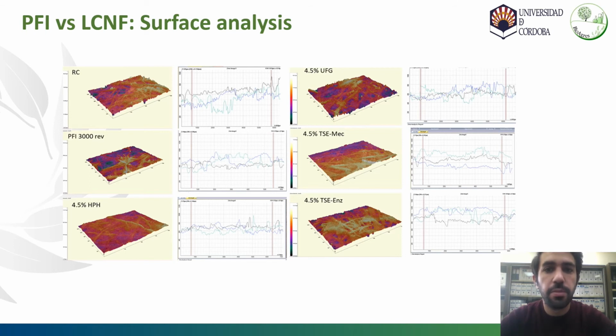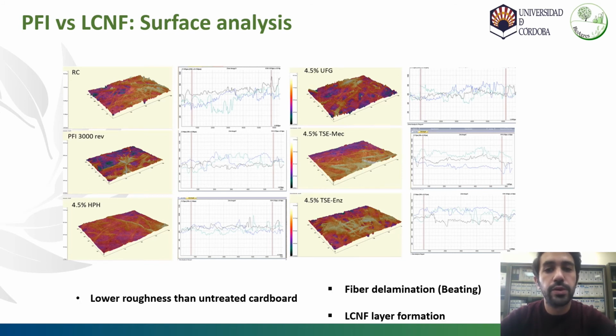It was also studied how the reinforcing effect of the lignocellulose nanofiber and the mechanical refining affect the roughness of the paperboard in comparison with the initial recycled substrate. It was obtained by laser profilometry that both the addition of lignocellulose nanofiber and mechanical refining produce papers with lower roughness than the untreated paperboard, due, in one case, to the delamination of the fibers in the refining, and to the formation of a surface layer of lignocellulose nanofiber that produces this smoothing of the paperboard.